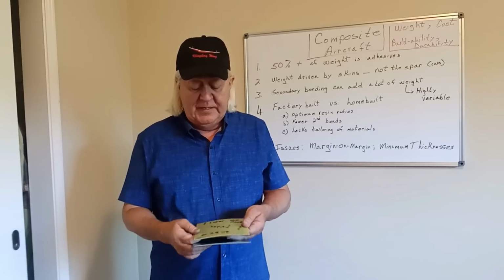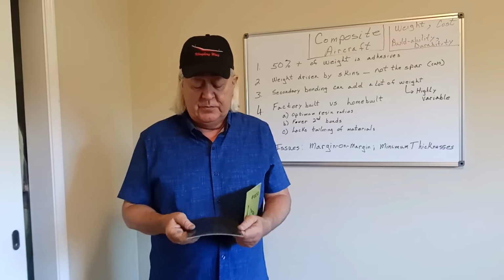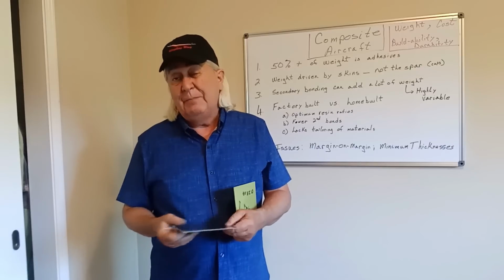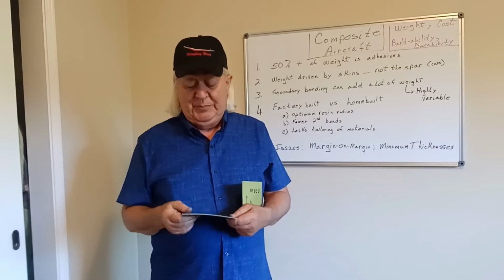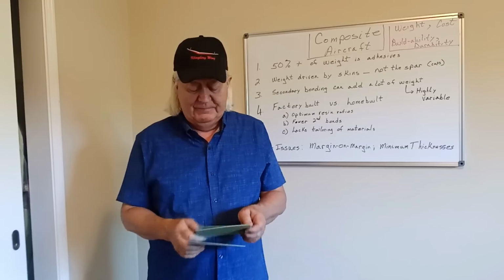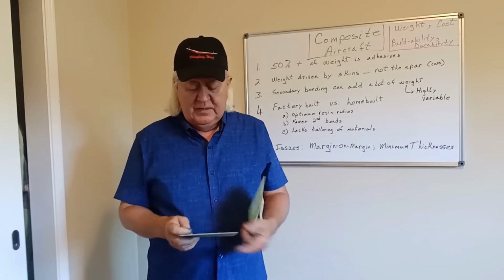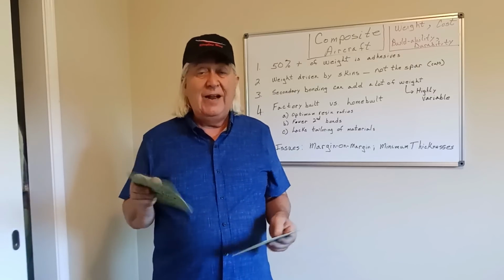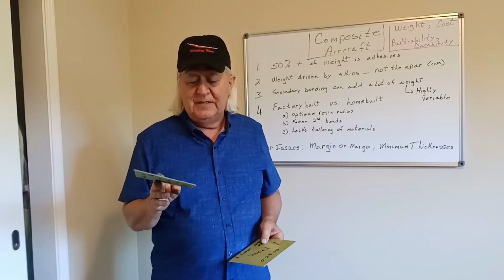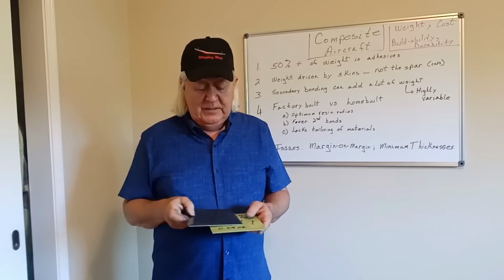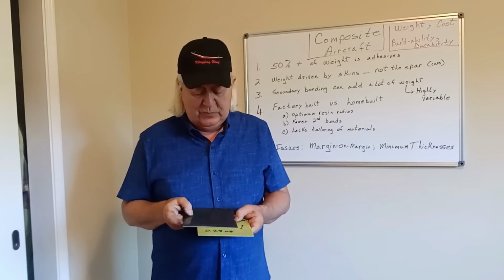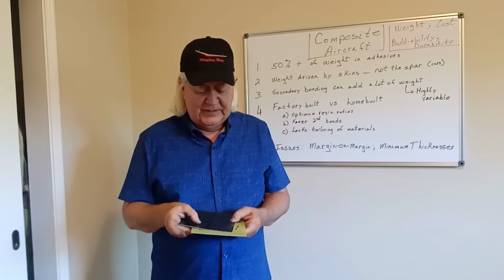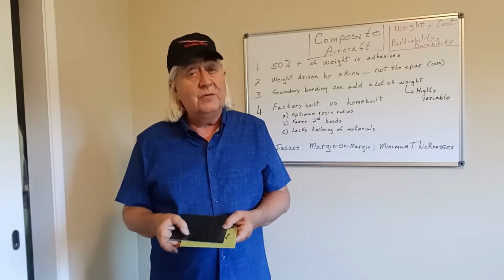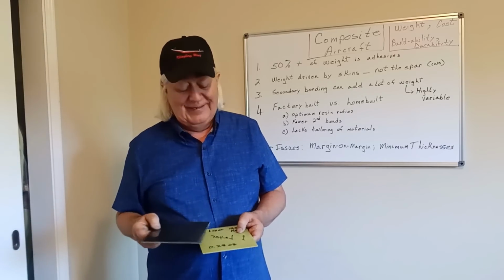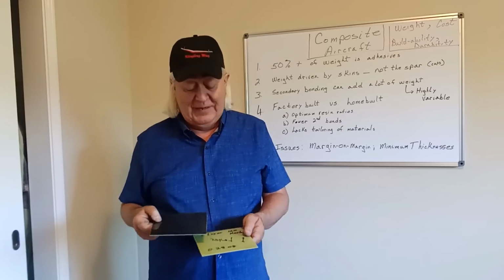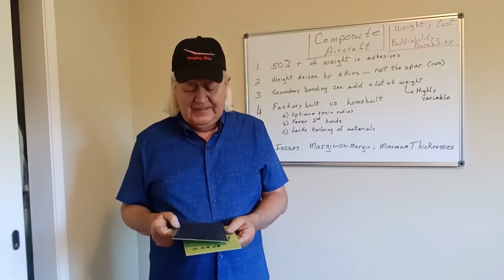And then I looked at bending, bend this one. It's about like the bentonite clay one, just a little bit stiffer, not a whole lot. If I play with them here, I can tell there's ever so slight more stiffness on this. And now down to what really counts. What we really wanted to see was the dent resistance. And you know what? Oh, no difference. It's about the same as the bentonite clay one. Ever so slightly better than the 1 layer Kevlar.